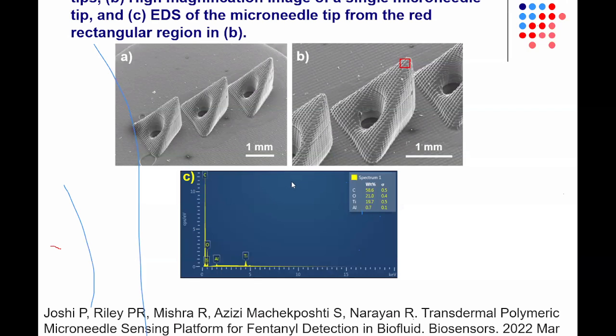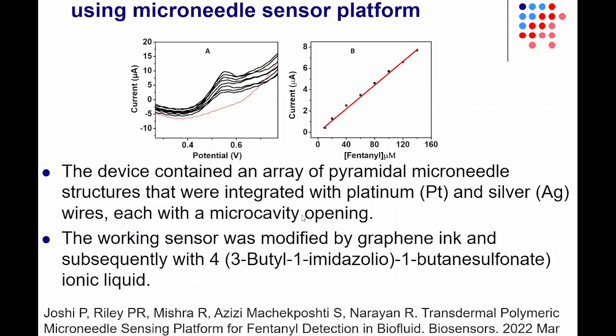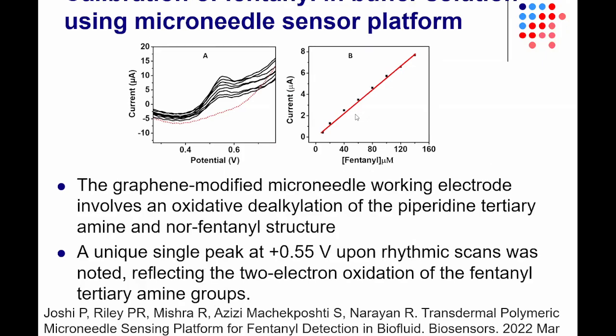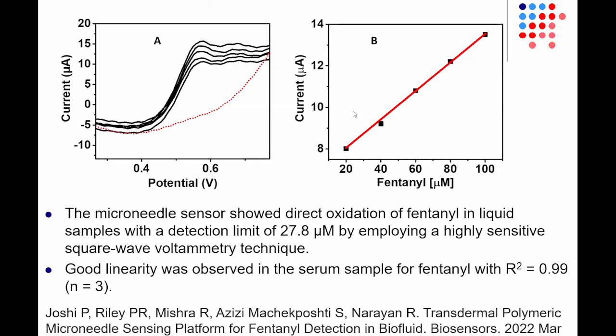Here you can see another example where we have 3D printed microneedle arrays being used for detection of fentanyl, an opioid drug of abuse. And you can see here this is an approach involving a graphene ink. It's modified with an ionic liquid. Here you can see that the chemistry involves oxidative dealkylation of the piperidine tertiary amine in the fentanyl structure. And you can see here that through this direct oxidation of fentanyl, you get a limit of detection of 27.8 micromolar.